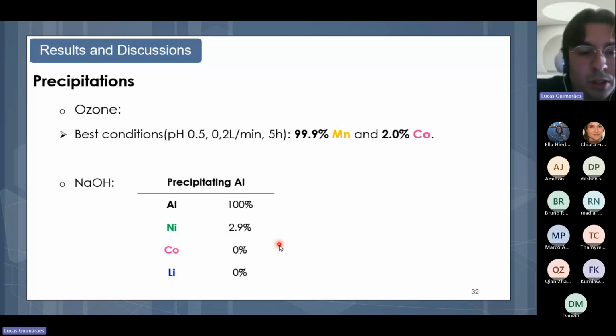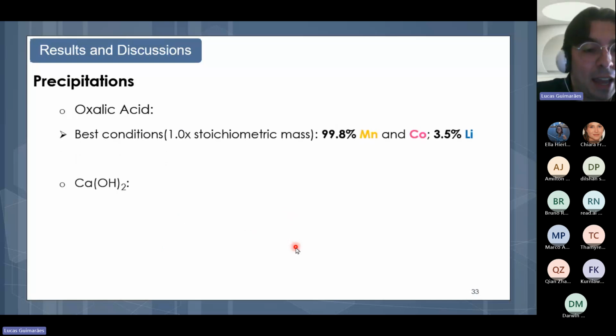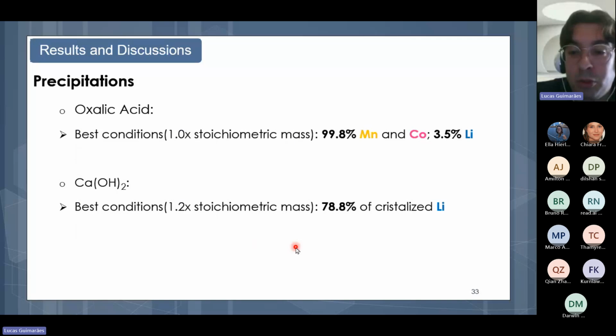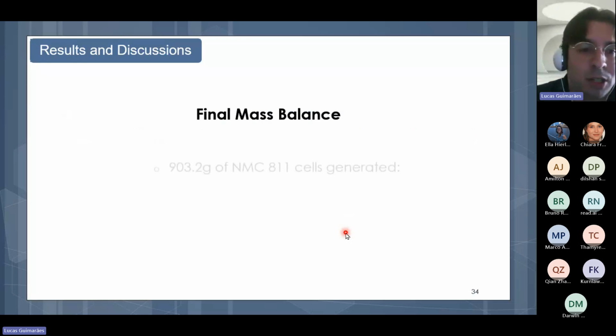And for the precipitation with sodium hydroxide to precipitate aluminum, at the best condition it was possible to guarantee 100% of aluminum. So all aluminum was precipitated, and the smallest amount of nickel co-precipitated was 2.9%. The precipitation with oxalic acid, in the best conditions, recovered 99.8% of manganese and cobalt, and only 3.5% of lithium was co-precipitated. The precipitation with calcium hydroxide at the best condition made it possible to obtain 78.8% of crystallized lithium in the form of lithium hydroxide.